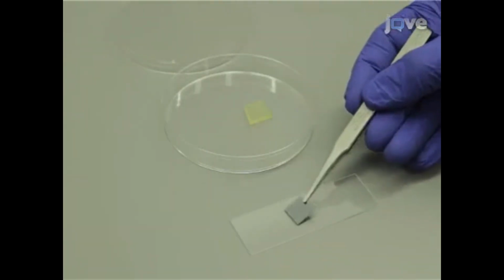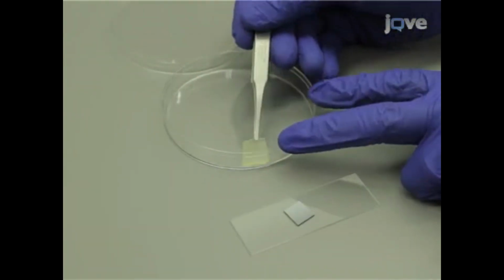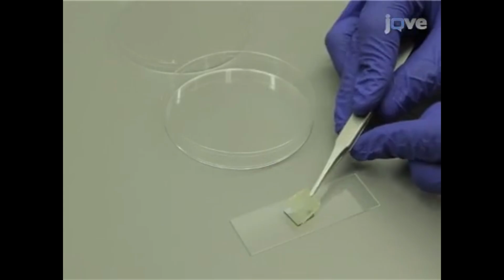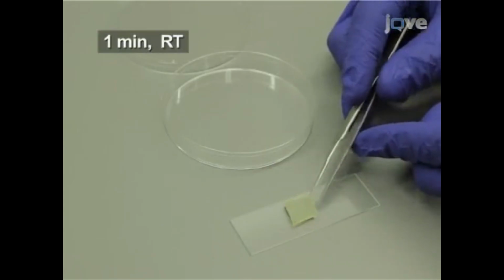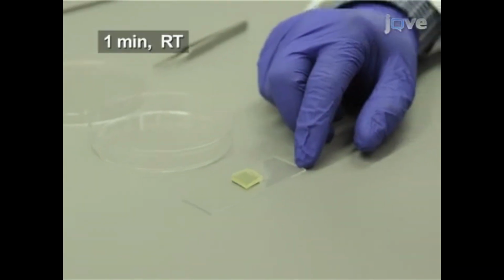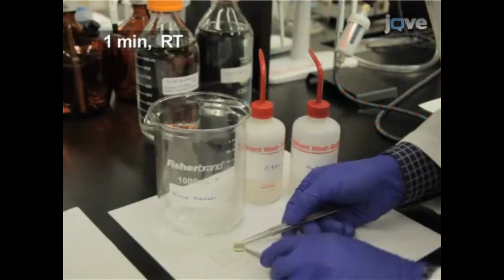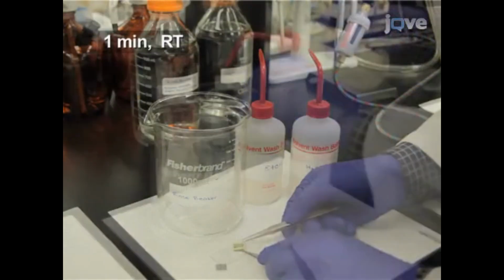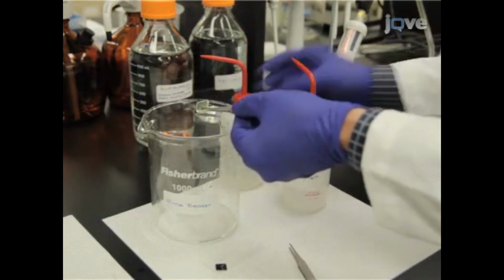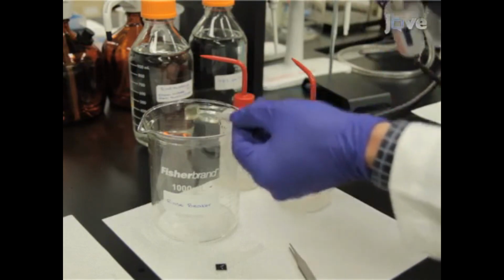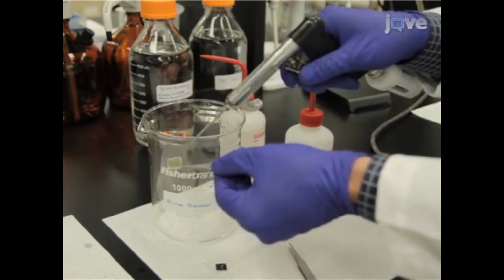The following is the most important step to the protocol. Place the stamp on top of the NHS-modified substrate with no external load to hold them together. Do not shift the stamp or apply too much pressure. Wait 1 minute, then rinse the substrate and stamp with ethanol, water, and then ethanol again, followed by drying under filtered nitrogen. Store the stamps at room temperature.